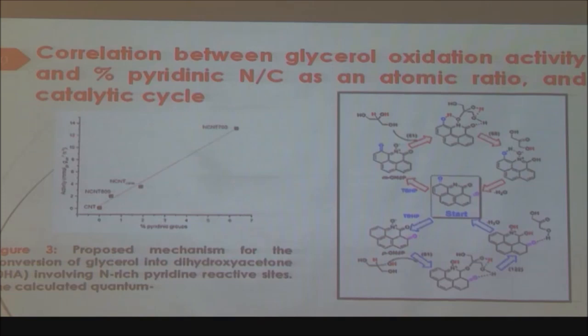The conclusion of this story was that if you have a pure pyridinic nitrogen, it may not give you the selectivity. The selectivity can be attained only if the adjacent oxygen atom is there. Both of them are required, but here the second one is here. When this type of structure is there, it was giving us more selectivity as compared to this pathway where the second oxygen is here. So oxidized CO groups adjacent to the nitrogen atom were found to be very active for this oxidation process, and we have identified these groups in our XPS study also.